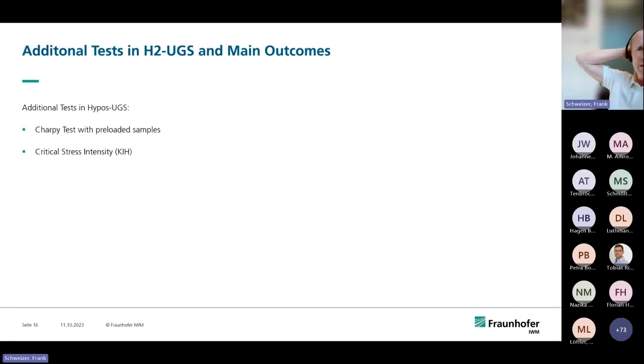So we also did additional tests in the HYPOS UGS project. We did Charpy tests with preloaded samples, but we were not so satisfied with the results. I think there has to be more work to do with that. The main problem with ferritic steels is that the hydrogen gases out in short times. And we also measured the critical stress intensity, but for the X56 steel, we could just say the steel is too ductile for this type of measurement.